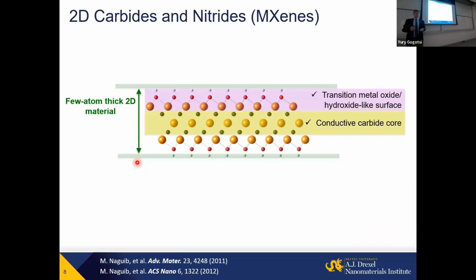They are also terminated by typically oxygen, OH, or, as you will see later, you can have halogens, chalcogens here. So they're metals that actually can have on the surface transition metal oxide-like, hydroxide-like, chalcogen-like termination that can change the oxidation state without killing its metallic conductivity. You know, in graphene, you make a graphene oxide, conductivity drops down by 7 orders of magnitude. In MXene, it won't change.